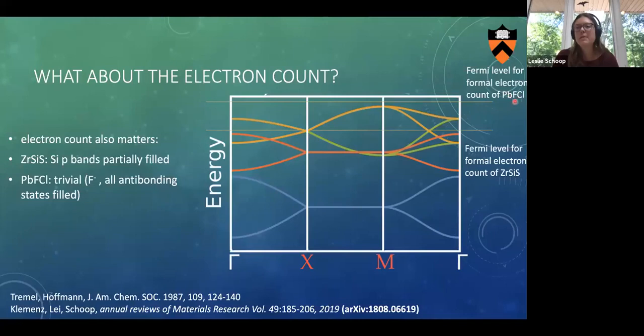And we don't get the Fermi level at the right position. What the hypervalent bond does for us, the delocalization, is that it pins the Fermi level here at the interesting position. Okay, this is why the chemical bonding becomes interesting and important. And so now what can we do with this once we learned it?